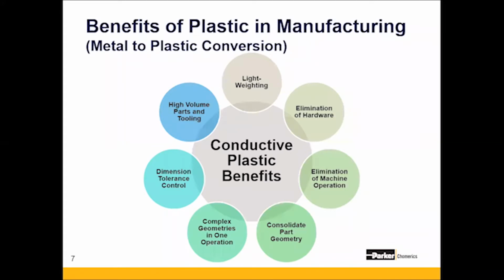Additionally, tolerance control with conductive plastics or plastics in general is on par with the highest of machined parts. So you're looking at tolerances of 1 to 2 thousandths, and actually far more accurate than what you would see with die cast and sheet metal parts. Additionally, while the tools for plastic parts may have an upfront cost, they're going to last nearly 10 times longer, yielding upwards of 1 million parts before scheduled maintenance instead of in the tens of thousands with things like die cast.